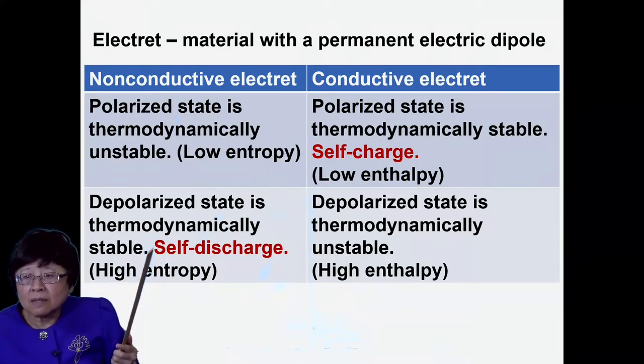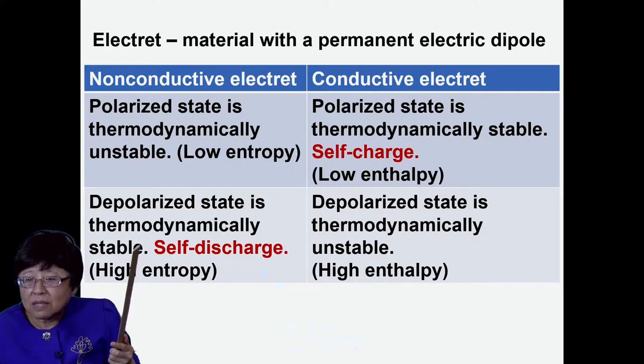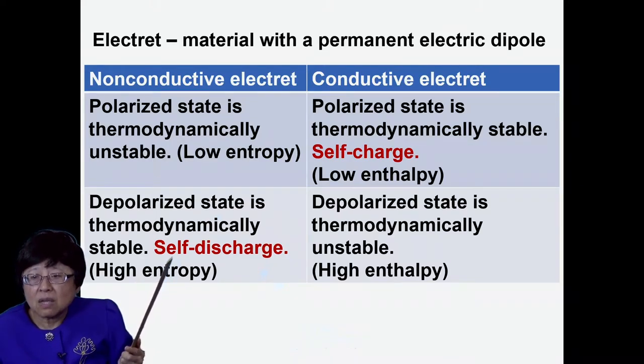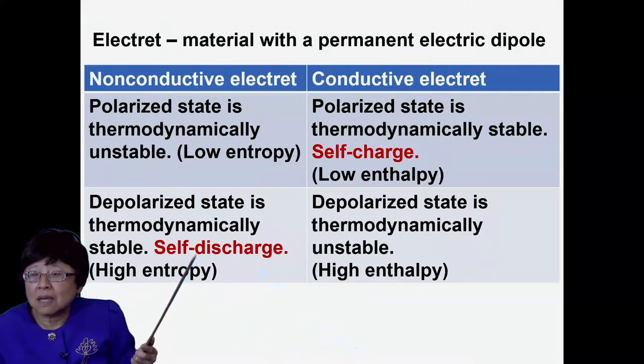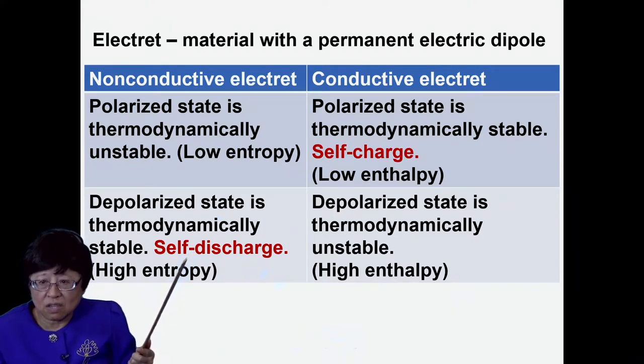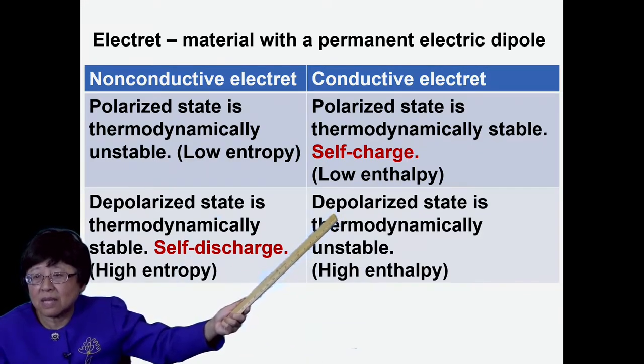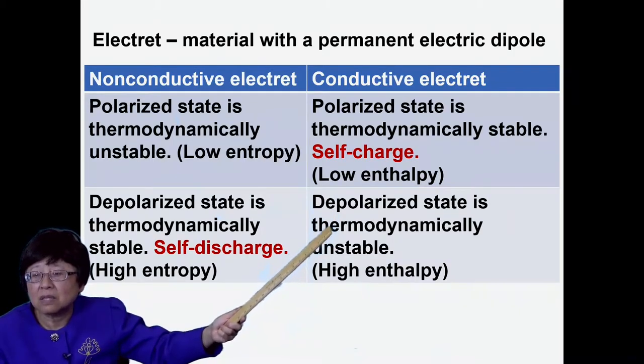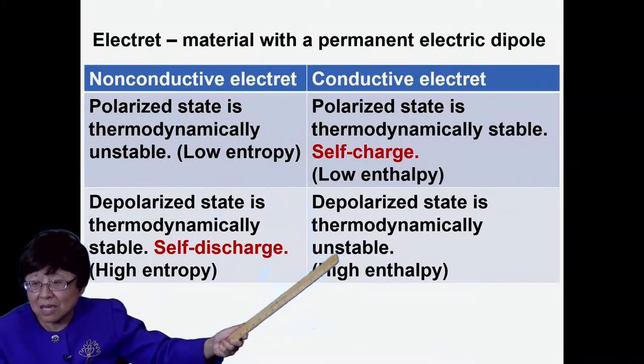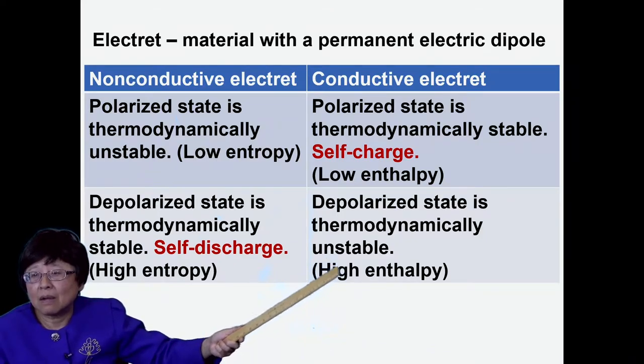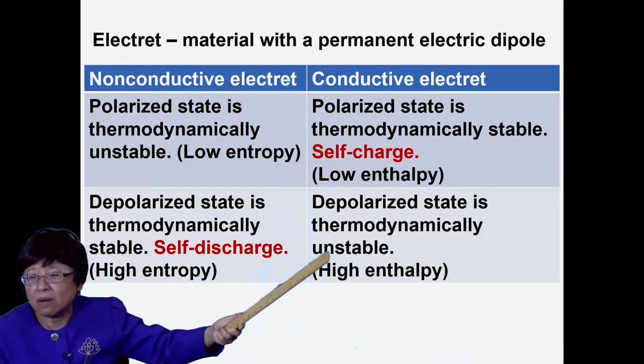For the non-conductive electret, the depolarized state is thermodynamically stable, because of the high entropy involved with the randomization of the dipole orientations. And so non-conductive electrets would self-discharge. If you let it sit, it would discharge automatically until it's no longer polarized. However, the depolarized state of a conductive electret is thermodynamically unstable, in contrast to the stability of the polarized state.